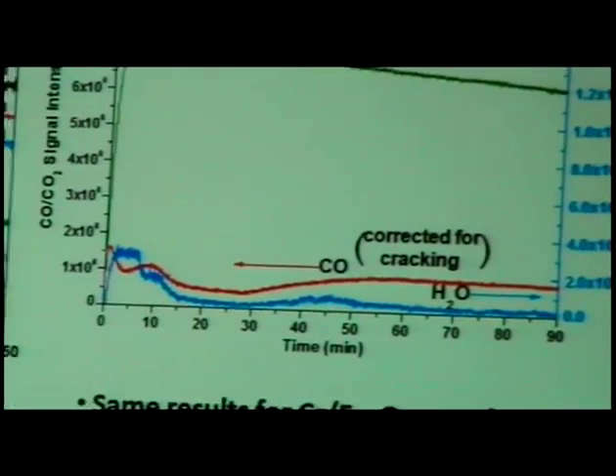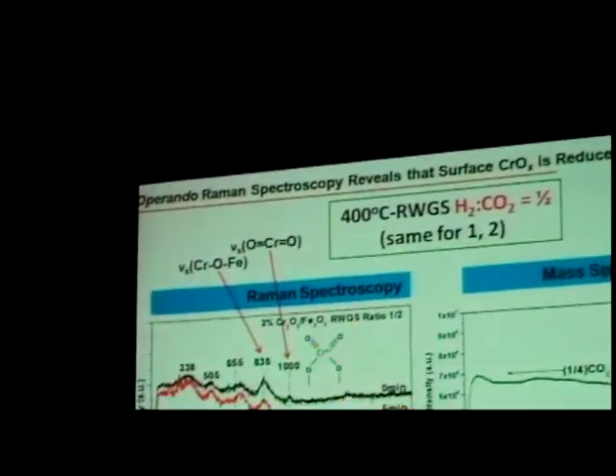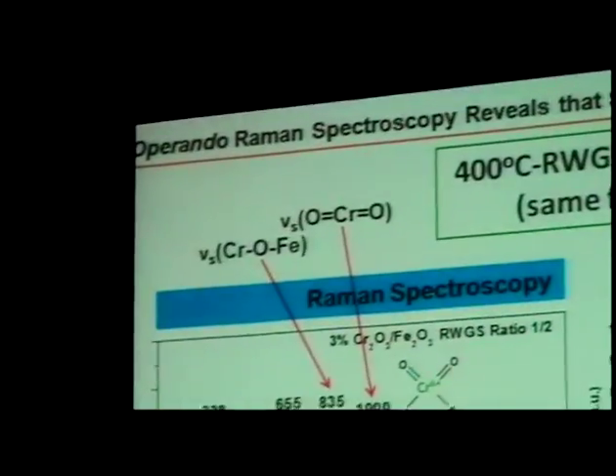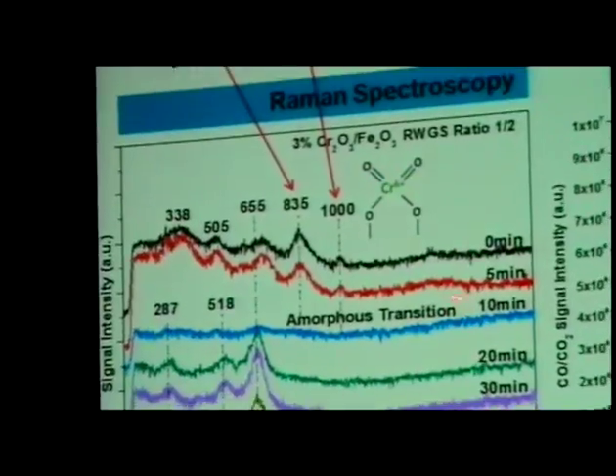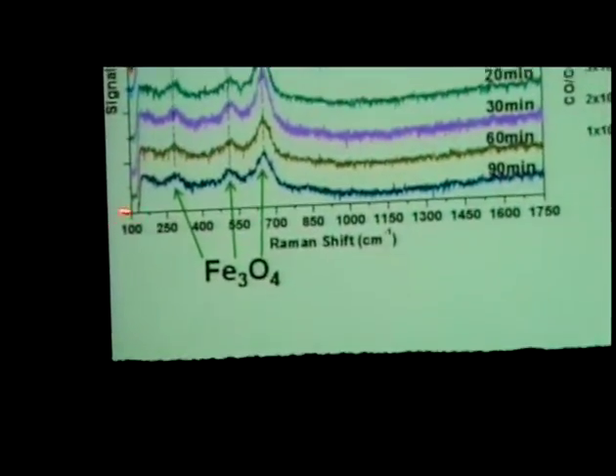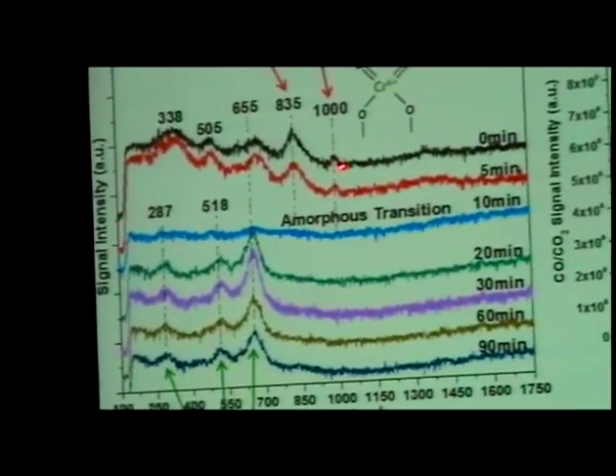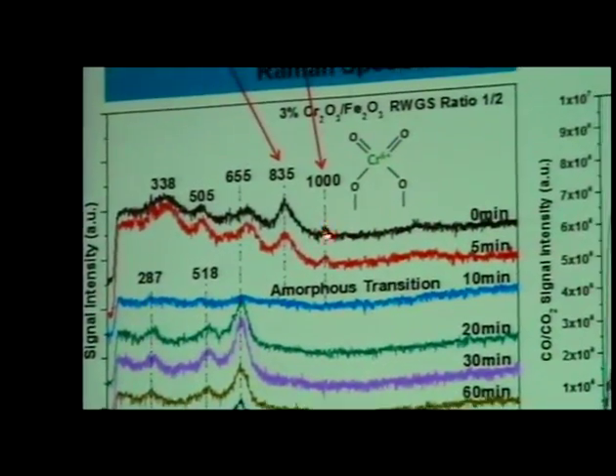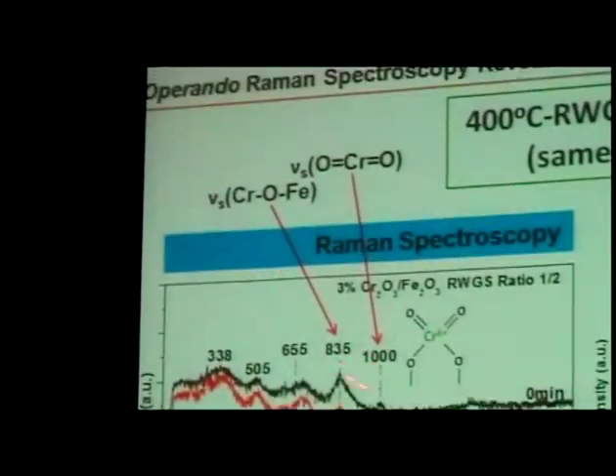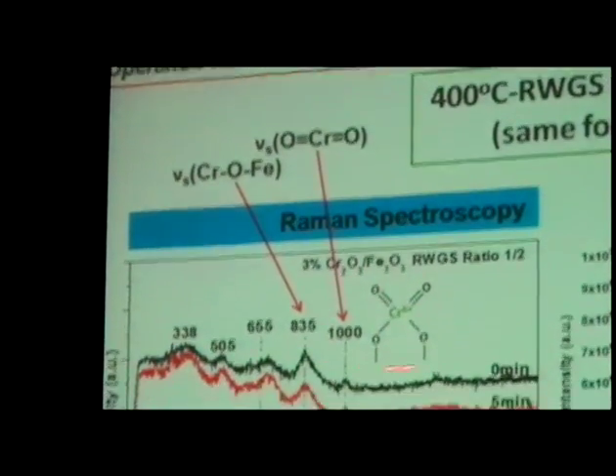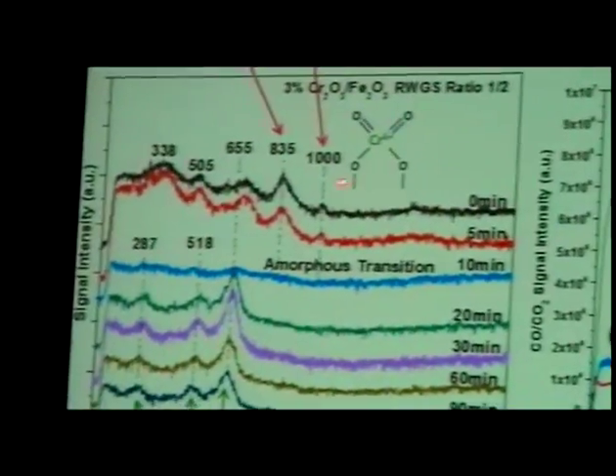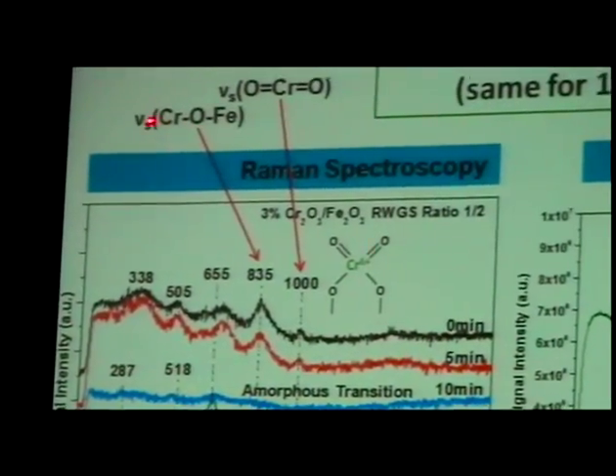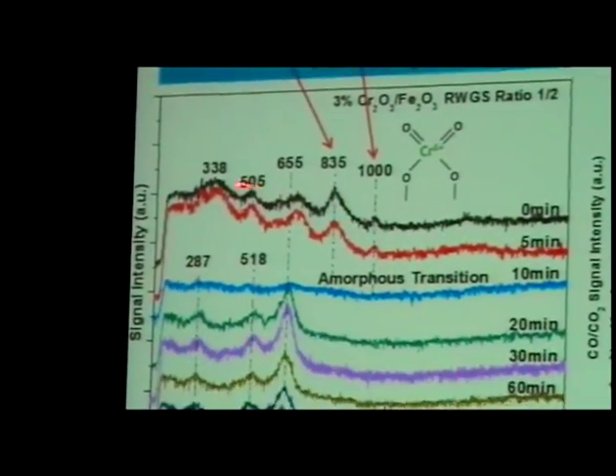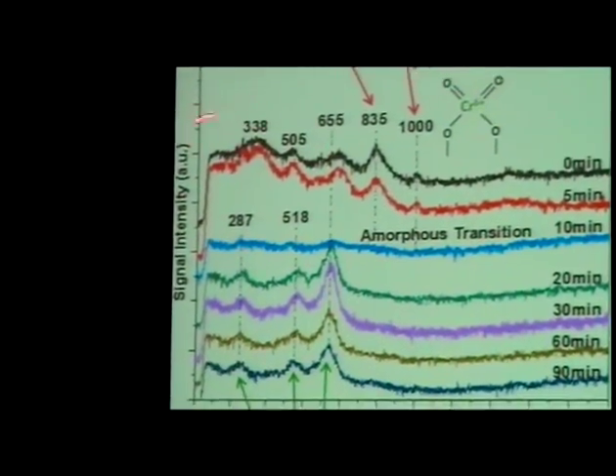This is the mass spec signal just showing that we're doing water gas shift during this time. What about the surface? So again here we're looking at Raman spectroscopy. Now this time we've added the chromium to the catalyst, and again this is the Raman intensity, and here are the vibrations. At the beginning of the reaction, you have this band at 1,000 wave numbers. This band is the structure of dioxochromium 6. And there's a stronger band here at 835. It's the bridging chromium-oxygen-iron band. And these are the iron oxide Fe3O4 bands.